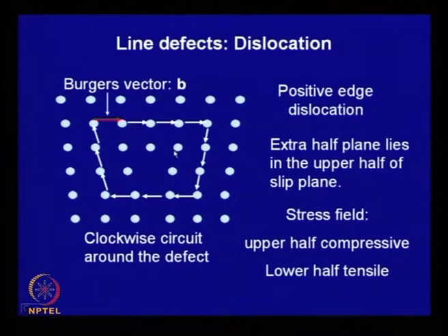So, if you try to move this dislocation, if you do a positive work, this displacement is like this. On the bottom side it is opposite to the Burgers vector. The Burgers vector is a displacement vector, so here the work done is negative. So, in a way, to move this dislocation from this end to the other side, you do not spend much energy. That is why, by assuming the crystal contains a line defect called dislocation, it is possible to explain why the shear stress required to cause slip is so low.